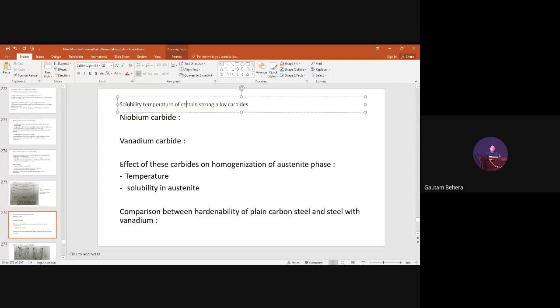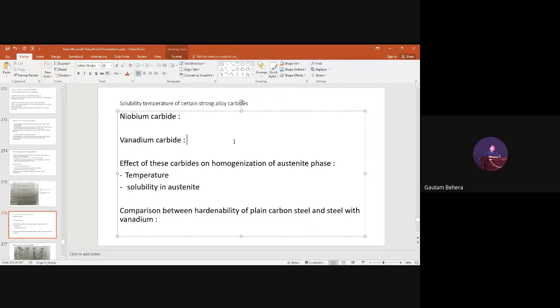Now there is a concept here, as I told, the solubility temperature of certain strong alloy carbides. They are ferrite stabilizers which basically form strong carbides. The best examples are niobium carbide and vanadium carbide, and titanium carbide also. They are very stable carbides. They do not easily get soluble in the austenite phase. They require very high temperature. So here basically we are talking about niobium and vanadium.